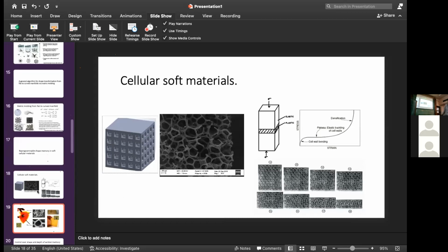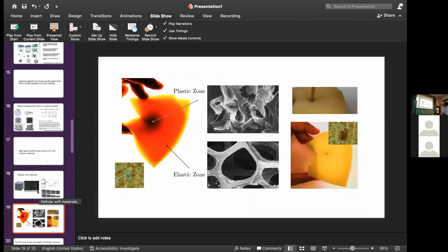But okay, so what I've done here is that I compressed it on one side for demonstration purposes. What's happening on the microscopic scale is that these rods are buckling and getting connected to each other by friction, by frictional coupling. And if I now poke the system with an indenter, whatever deformation I've done to the system will stay.